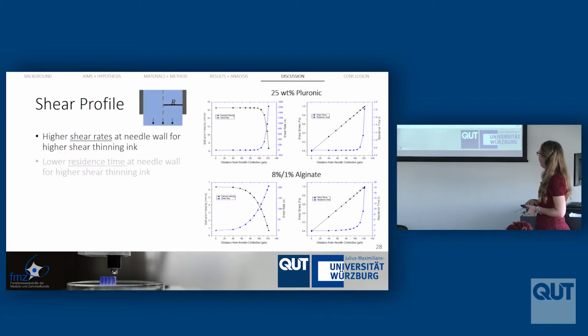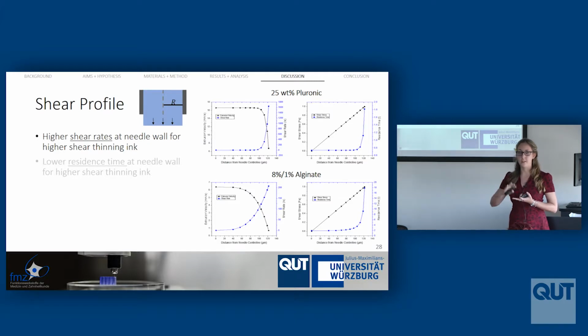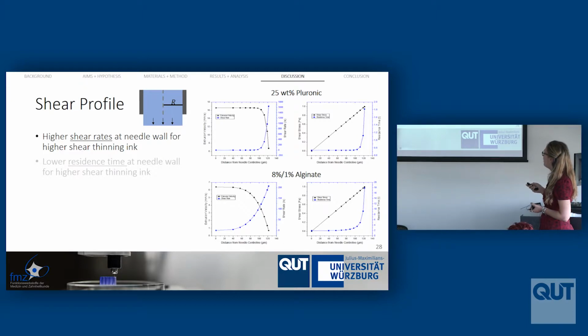There are a couple of other very useful mathematical results for this, and I'll just touch on them really, really briefly. The high shear rate, so this is the force that we're applying to the needles and also to the materials, and this occurs in the needle. High shear rates at the needle walls.